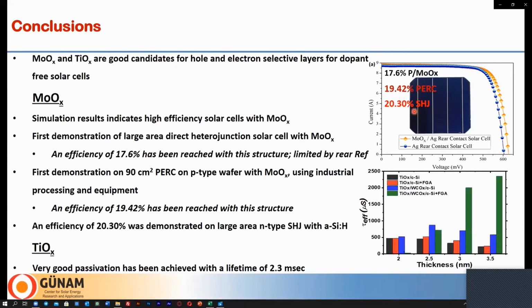From the loss analysis, we found the main losses arise from passivation, but mostly from the rear side optical response. Then we demonstrated more than 19% PERC with molybdenum oxide. This cell has improved short circuit current density compared to the direct molybdenum oxide P-type junction. And indeed, this PERC with molybdenum oxide is the first demonstration in the literature using an industry feasible process sequence and tools.